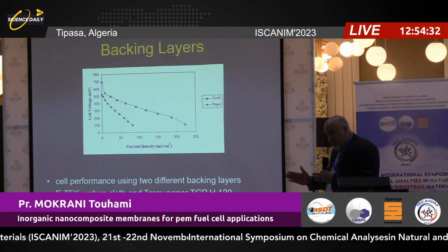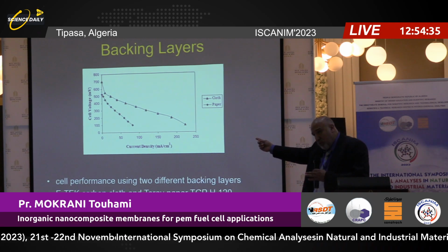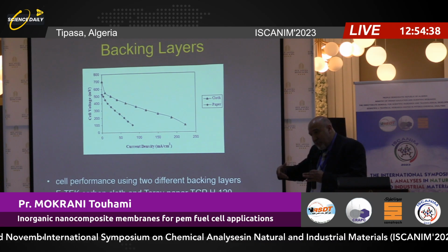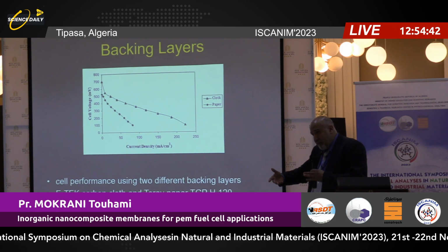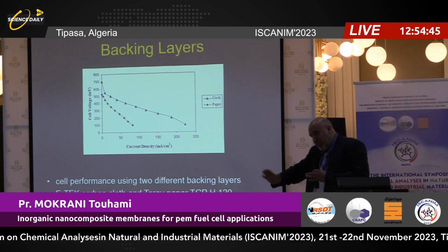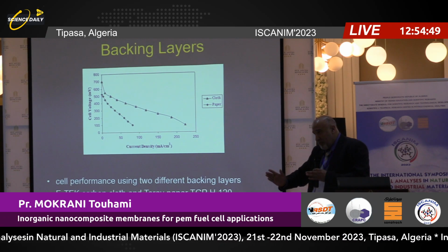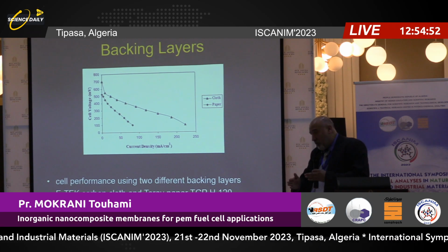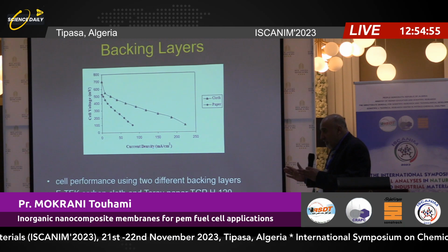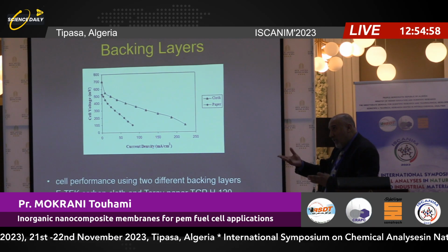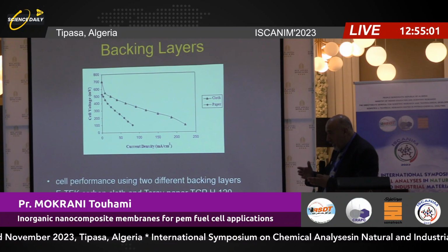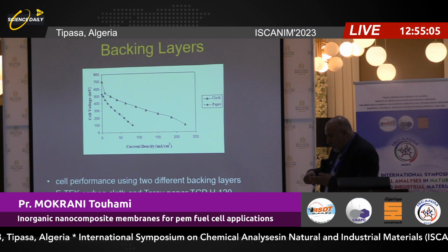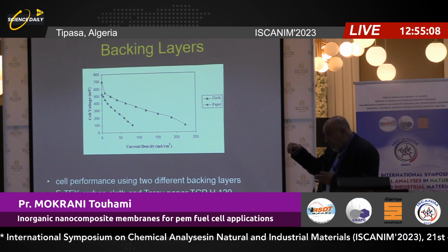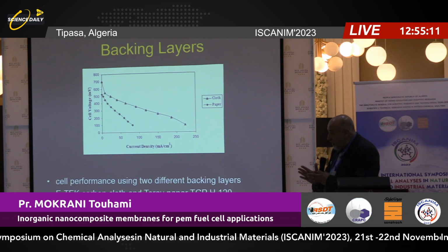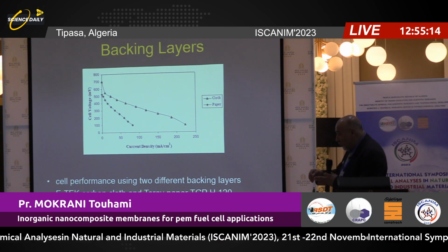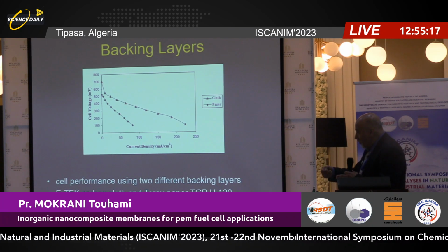Then the electrode they prepare is the optimal one they showed you. They mix what they prepare into an ink, including Nafion solution. It's a very specific way of preparing it. Then they spray it on the GDL. They tried first on the membrane, but it's very difficult, so they put it on the GDL. Then they do what they call hot pressing. They heat it to 180 degrees, which is the glass transition of Nafion. So Nafion in the membrane will be soft, Nafion inside the electrode will be soft, and then they press it together and form the MEA. So when you go and buy an MEA, they don't tell you how they make it.